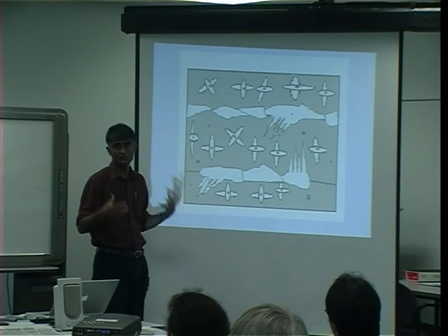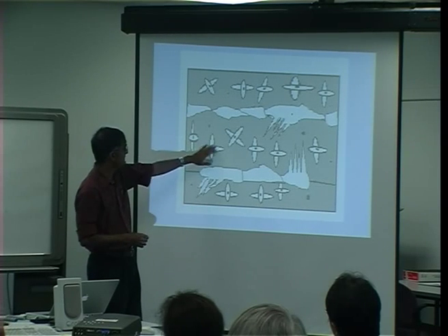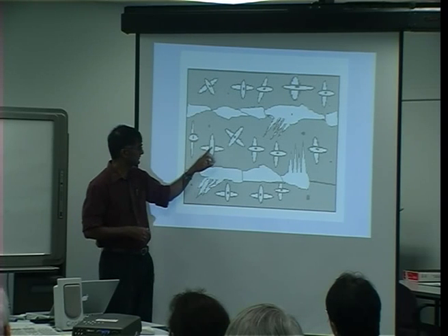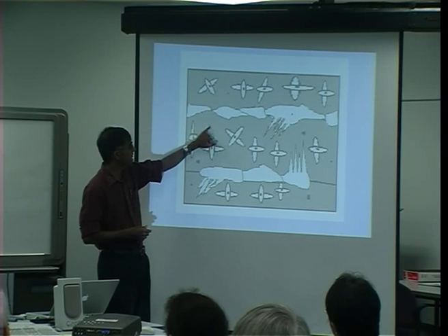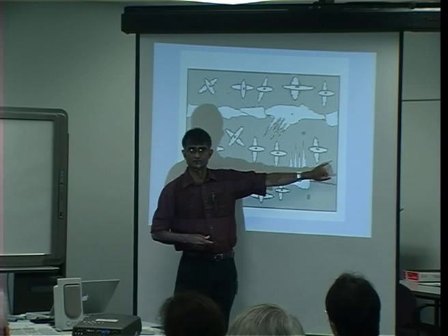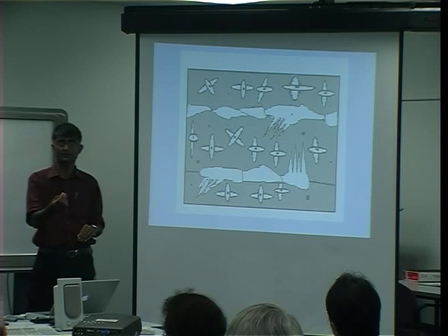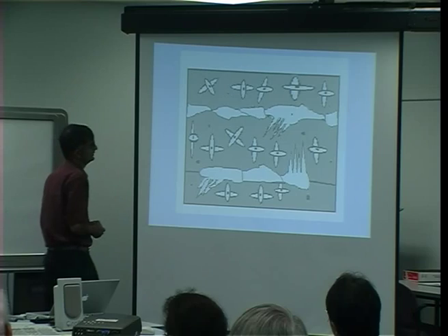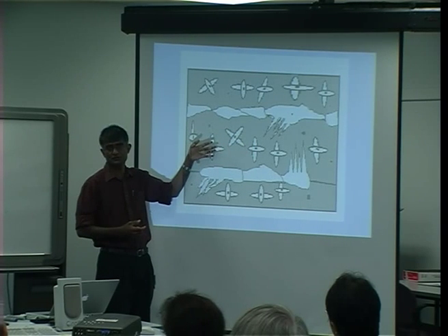And in welding terminology, that's called acicular ferrite, simply because these things appear like needles, although they are plates in three dimensions. And the reason why this is mostly limited to weld deposits is that they nucleate intragranularly on oxide particles which are present in the weld. So those are heterogeneous nucleation sites, and those oxides can be very complicated mixtures of many different kinds of compounds. But that is the sort of desired microstructure.